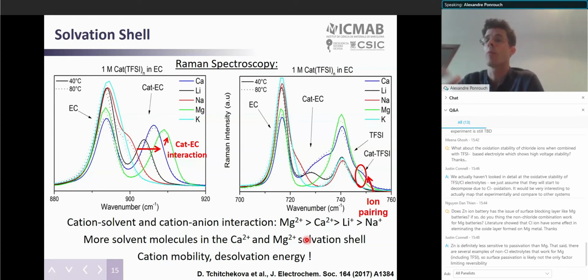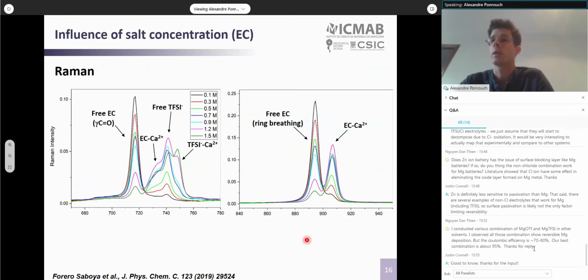So we have a much more bulky cation complex to move around in our electrolyte, which will of course be an issue in terms of mass transport in our electrolyte, which can also affect the overall kinetics of the process. With this in mind, we try to reinvestigate several electrolyte formulations, specifically paying attention to the impact of the salt concentration.